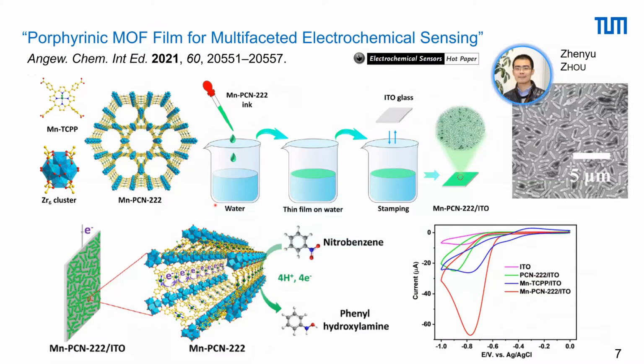So what Zhenyu did is the following. We took from the literature a recipe of a known so-called PCN metal organic framework, which is a porphyrin-type system, which has this kind of hexagonal channel structure. You can synthesize a whole series of related MOF materials of that kind. They are very hydrophobic, and they do us a favor to nicely spread on the liquid-air water interface. And this gives you the opportunity to transfer them to a substrate. It can be ITO, it can be different things.